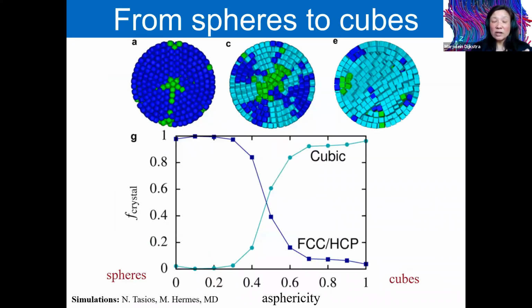We also analyze this as a function of the roundedness or the asphericity of the cubes. Here we start with spheres and then we go towards the cubes. If we calculate the fraction of FCC, HCP, or simple cubic, we see that the cubes form almost 100% simple cubic crystal structures, whereas the spheres form 100% FCC or hexagonal close-packed structures. And in the middle, it crosses over from FCC to cubic.